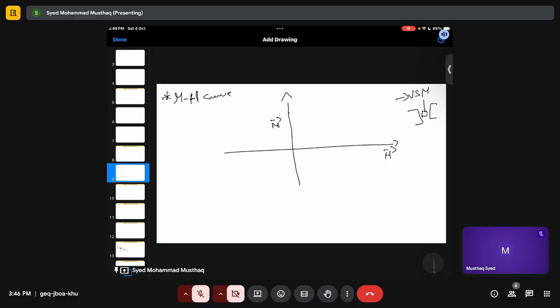So how do you do that? For example, you will have a very thin strip. You put your sample here. You have very strong magnets facing north and south pole. So you have a magnetic field, and you start vibrating your sample up and down. Because of this vibrating, there is a change in magnetic flux, and the change in magnetic flux interacting with your material will generate electric current.